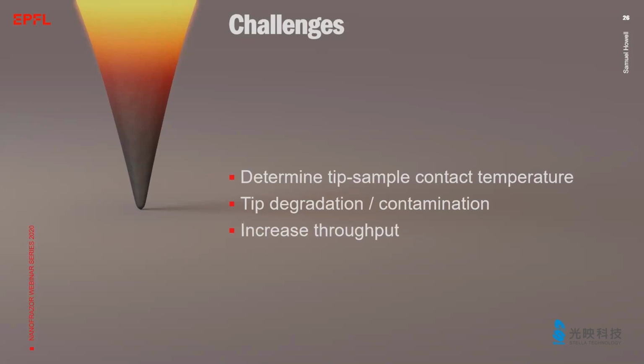A more important issue is degradation and contamination of the tip. Here, the focus is on developing resist materials that convert or decompose without leaving residues on the tip. And finally, in order to become industrially relevant, the throughput of TSBL has to be increased. Solutions towards increasing the throughput exist, such as increasing the number of tips that can be actuated in parallel. Hybrid thermal lithography, where a laser and a tip are used in the same tool, is another strategy.